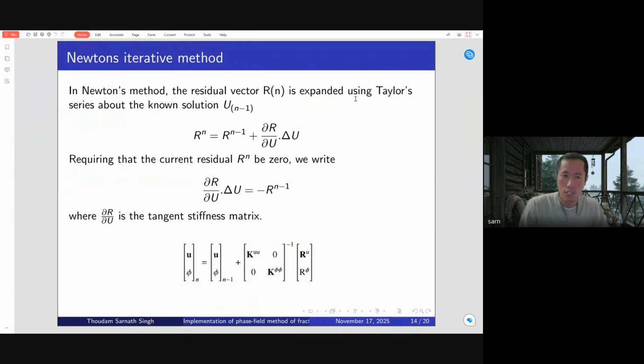By using the Taylor series expansion, we can expand the residual vector as Rn equal to Rn minus 1 plus dou of R divided by dou of U into delta U. This U can be displacement, it can be phase field phi, it can be any other field depending on what we are solving. And I have neglected the higher order terms. We want the residual to be 0. So if we make this residual 0, then this expression can be written as shown here.